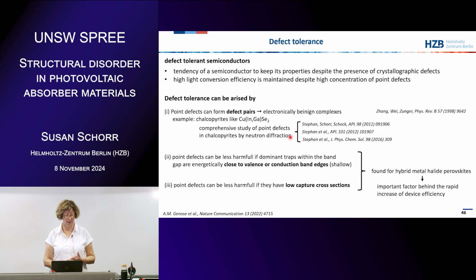So, there are different properties by which you can get defect tolerance. For instance, in the chalcopyrites, so copper, indium, gallium, selenide, we studied this intensively in these papers, for instance. There are a lot of defects, in this case 10 to the 20, 10 to the 21 per cubic centimeter. But the material makes a good solar cell. And there is the theory from Alex Zunger. He came up with the idea that the defects form defect pairs. And so the energy level of the defect pair is then shifting to a shallow level. They are not in the middle of the band gap anymore. And with this, they are not harmful anymore.